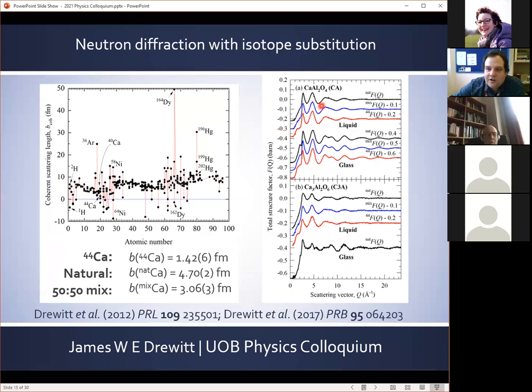So here I show the neutron diffraction with isotope substitution measurements for the equimolar calcium aluminate liquid and its glass, and the tricalcium aluminate liquid. We can see that between the natural mixture and 44 structure factors, there's a contrast, at least in this low Q region, due to the different weighting factors on the correlations involving calcium. And so we can subtract and make linear combinations of these structure factors in order to isolate or eliminate specific pair correlations of interest.